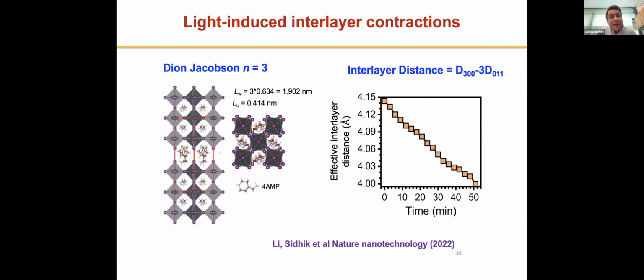The next thing we wanted to look at is, if we are indeed bringing these layers closer, what is the change in the interlayer distance? Because this is of course interesting from a fundamental perspective of looking at photophysics and excitations across these layers. But from a perspective of transport, we wanted to see if we were actually bringing these layers close enough that we could then induce a transport channel in this out-of-plane direction.